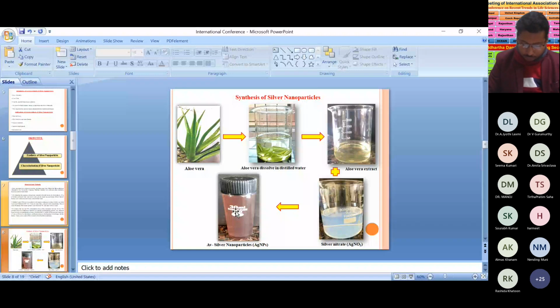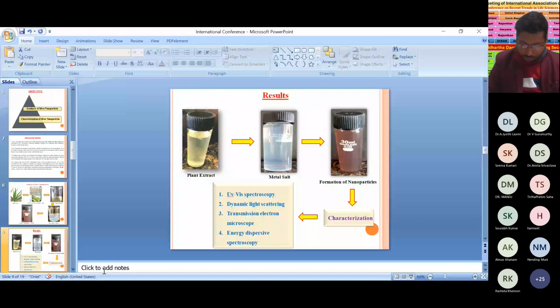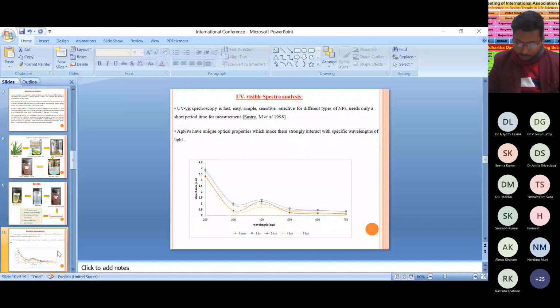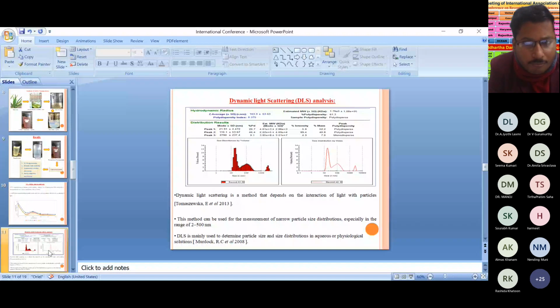DLS is a method that depends on the interaction of light with particles. This method can be used for the measurement of narrow particle size distribution, especially in the range of 2 to 500 nanometers. DLS is a non-destructive method used to obtain the average diameter of nanoparticles. And next, TEM, transmission electron microscope. TEM is a valuable, frequently used, and important technique for the characterization of nanomaterials. TEM shows 10 to 50 nanometer spherical aloe vera silver nanoparticles. The magnification of TEM is mainly determined by the ratio of the distance between the objective lens and the specimen, and the distance between the objective lens and the image plane.